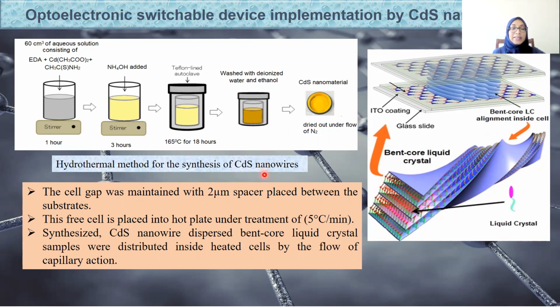Bent core liquid crystal was then fabricated, and then the synthesized CdS nanowire was dispersed into the liquid crystal to form a nanohybrid composite. This shows the fabrication of ITO liquid crystal cell.